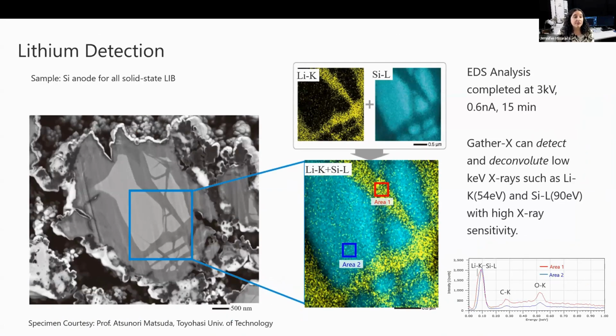And here's an example of a silicon anode from an all-solid-state lithium-ion battery material, which adopts a solid electrolyte between the cathode and anode. As you can see, the Gather-X can not only detect the lithium, but it can also deconvolute the lithium K and silicon L lines, which are only 36 eV apart. Here you can see mapping with very good separation between the lithium and silicon areas, even with that strong overlap in peaks.